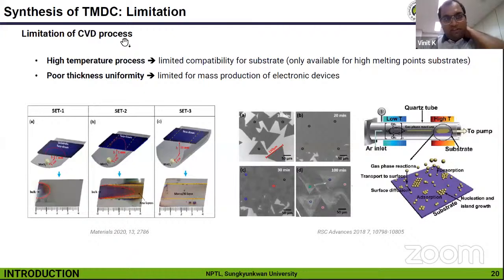And the CVD process. The main issue with this process is the high temperature and also the poor thickness uniformity, as shown here. We need the substrate temperature to be very high, more than 500 degrees Celsius in some cases, and in some cases almost up to 1000 degrees Celsius. Along with that, the thickness uniformity is also not good. We need to control many parameters to control the thickness.